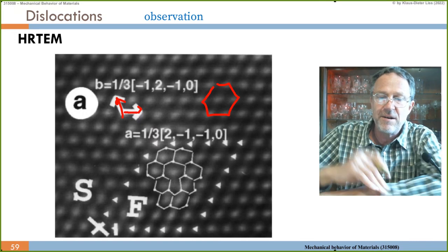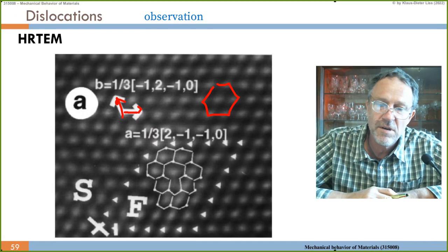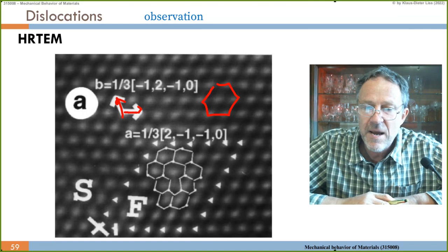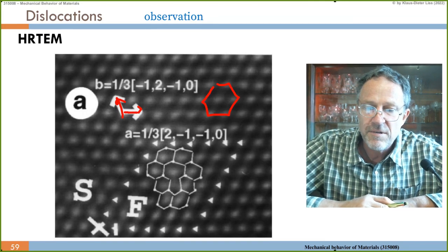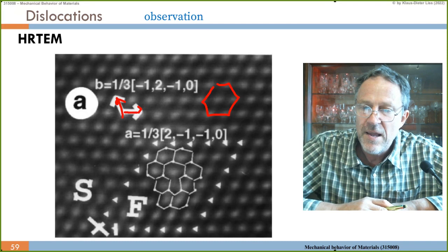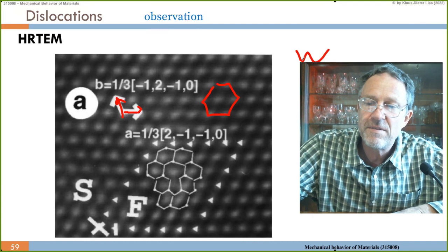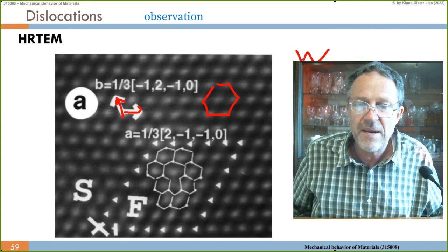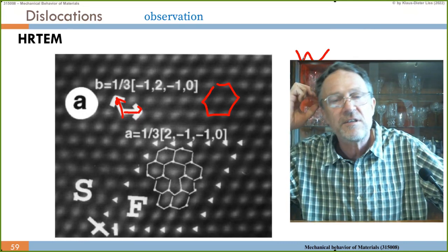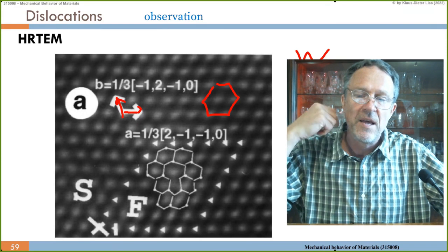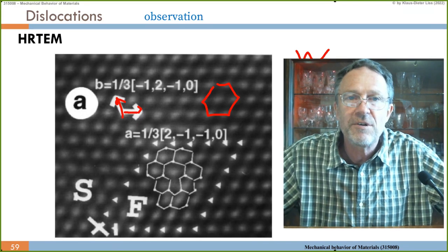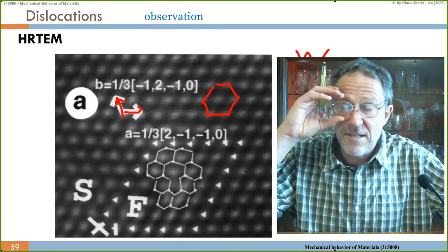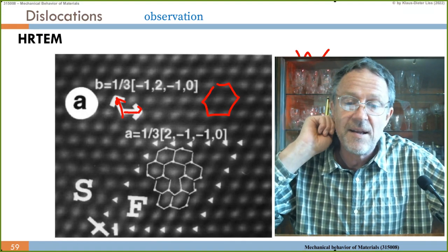One can find out now, but the question is, is there a dislocation or not? Sometimes if you remove all these markings and so on, it's difficult to find the location of a dislocation, particularly when the width W is very large. When it's very large, then the dislocation is distributed over many, many atoms, and you have difficulties to localize it. So you do the same trick as I showed you last time. You have to count the number of lattice translation vectors in one dimension and in the other lattice dimensions.